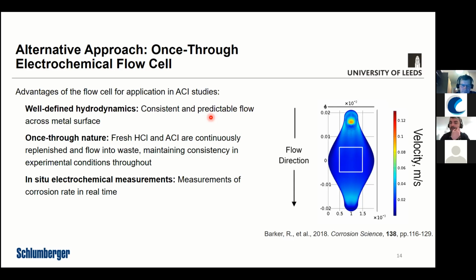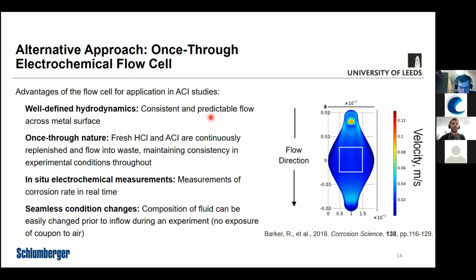For other flow cells that we've designed, we've also been able to do in situ imaging and X-ray scanning to understand when corrosion product layers are forming on the surfaces in situ. So they're a very useful technique for a number of different applications. Also pretty useful in this test is that we could have seamless changes in conditions. Simply by moving the tube into different containers of fluid, we could very easily change conditions in the cell without exposing the coupon to air.